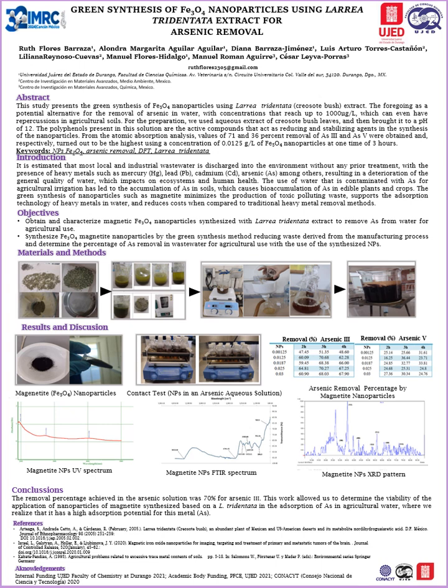To obtain the extract, a 1:10 plant material to solvent ratio was used, with deionized water acting as the solvent. This mixture was brought to a temperature of 60 degrees Celsius for 1 hour while continuously stirring, and later let it rest to cool down the solution. Lastly, it was filtered under vacuum to obtain the extract.